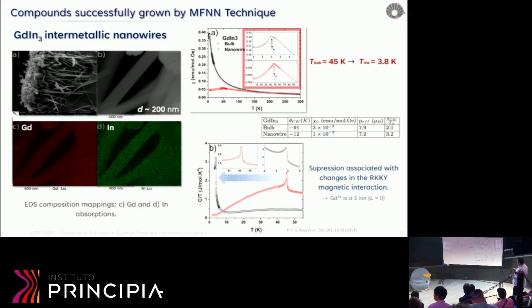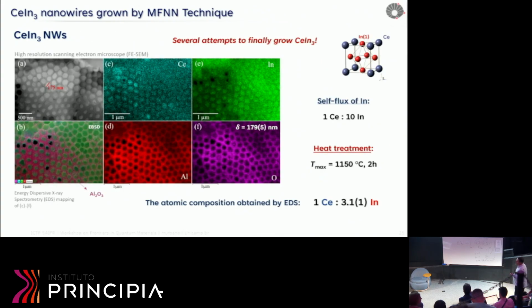So if you look at specific heat, it also displays this. This was interpreted as a frustration or suppression of RKKY magnetic interaction, because over here, gadolinium is an S ion, L equals 0, so it's not so complicated. But now, let's look at cerium indium-3.